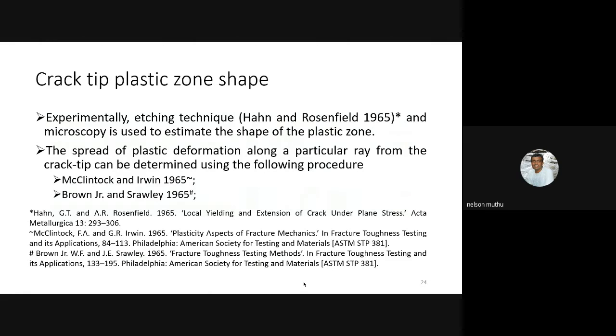How do we determine this crack tip plastic zone shape? Experimentally, you can make use of an etching technique or microscopy to estimate the shape of the plastic zone. You can see this literature, Hahn and Rosenfield, 1965, or you can also see this literature. They were able to estimate the size and shape of the plastic zone, and to a greater extent it was in good agreement with whatever I have shown. So that was the confidence in Irwin's model or Dugdale model.